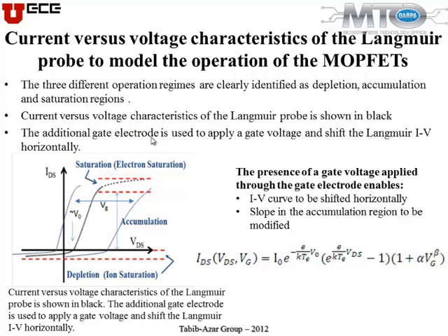The equations for IDS versus VDS as a function of voltage, you can derive them. It is very similar to what you get in semiconductors. So essentially, in semiconductors your dopants are fixed in the crystal, and then they produce the electrons or holes. Here you only have electrons. In here, the ions that produce the electrons can themselves move around. So it is kind of a fluidic semiconductor medium.